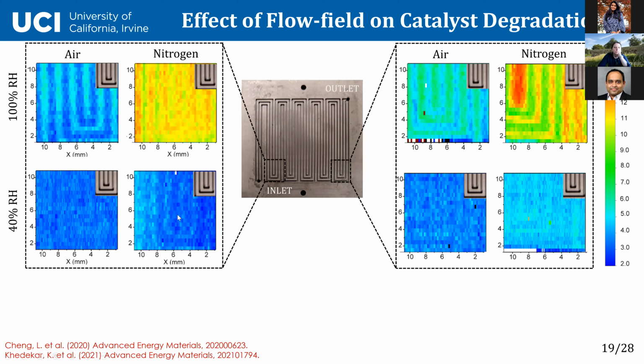Wet conditions, dry conditions. So what we see in dry conditions, actually, we don't see anything. We don't see inlet and outlet. Why do inlet and outlet matter? Because gases come from the inlet, they're getting consumed, more water is produced. So there are some inlet-outlet variations that are interesting. In dry conditions, we don't see much platinum particle size increase.